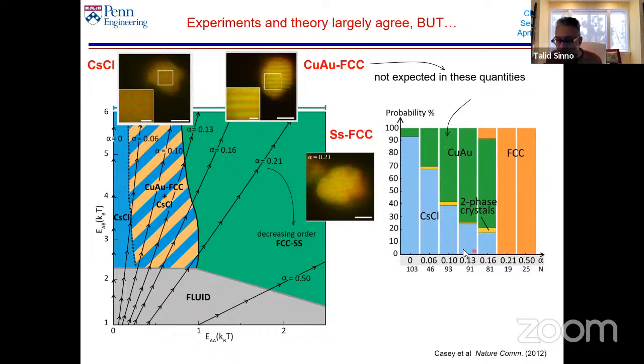By the time I get to 0.16, which is this, almost all of them are copper gold, very few are cesium chloride, and some of them are this orange color. So FCC orange means that I have an FCC crystal that is compositionally disordered. And so if you compare this picture to this picture, you'll see these have both the same structure, but the red and greens are randomly ordered here, and they're perfectly ordered here.